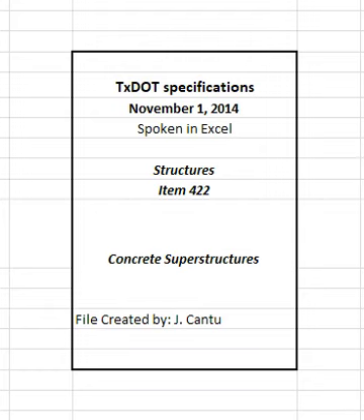3.2 Transporting and placing equipment. Use appropriate transporting and placing equipment such as buckets, chutes, buggies, belt conveyors, pumps, or other equipment as necessary. Do not transport or convey concrete through equipment made of aluminum. Use carts with pneumatic tires for carting or wheeling concrete over newly placed slabs.